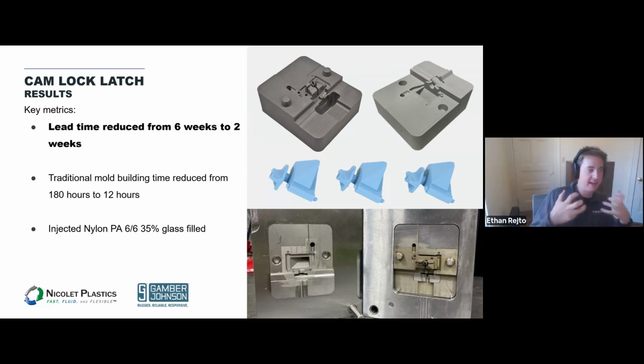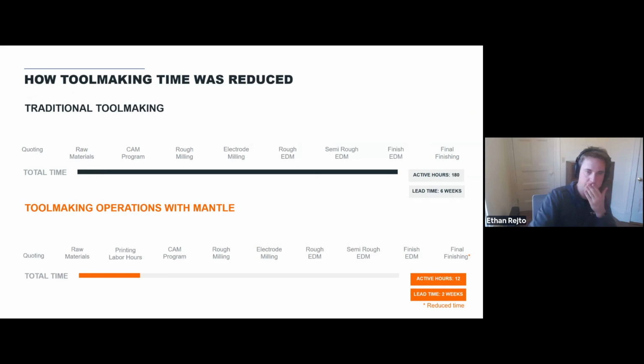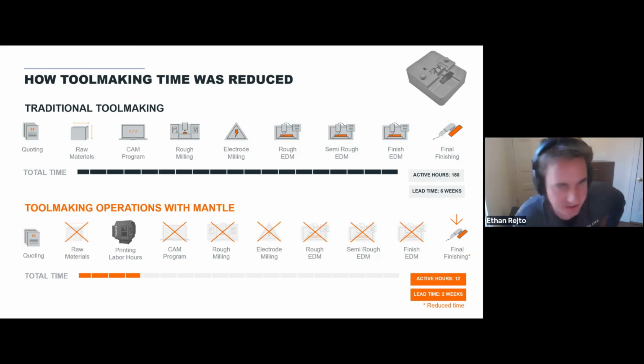They estimated the amount of active time for their tool makers to produce this down from 180 hours down to just 12 hours. And this was molding a 35% glass filled nylon, so a pretty abrasive material, they really benefited from the tool steel here with that high hardness. Looking at the steps again, really just removed most of the very, very costly and time-consuming steps of the process. All that EDM was taken out and allowed them to get from 180 hours down to 12, lead time from 6 weeks down to just 2 weeks.